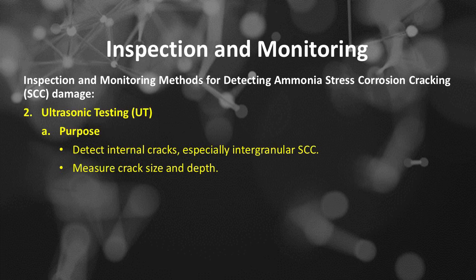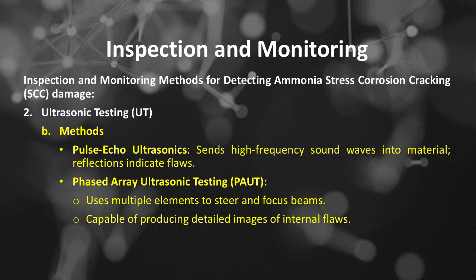Inspection and monitoring methods. Number 2 is ultrasonic testing, or UT. It is purposed to detect internal cracks, especially intergranular SCC. It measures crack size and depth. Ultrasonic testing methods include: the first UT method is called pulse-echo ultrasonics, which sends high-frequency sound waves into material, and reflections indicate flaws. The second UT method is called phased array ultrasonic testing, or PAUT, which uses multiple elements to steer and focus beams. Capable of producing detailed images of internal flaws.